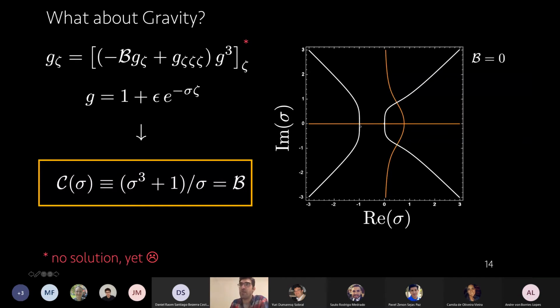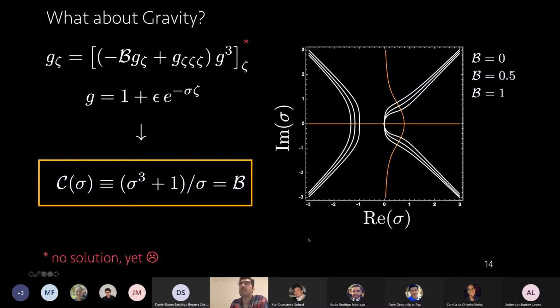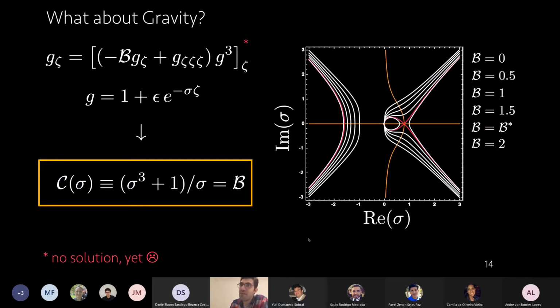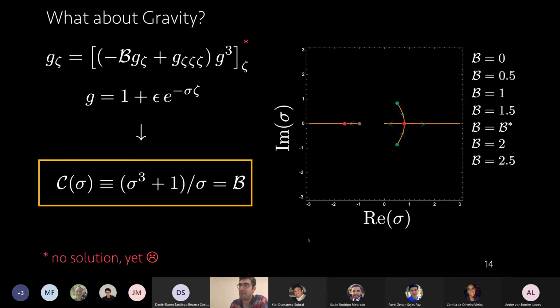So this is the solution for no gravity. You have 3 roots, 2 imaginary, 1 only real one, and then you start increasing your gravitational effect, and boom, you get a critical gravity, the critical Bond number. So it looks like, at least based on this equation, that even gravity at some point will result in the removal of these undulations.